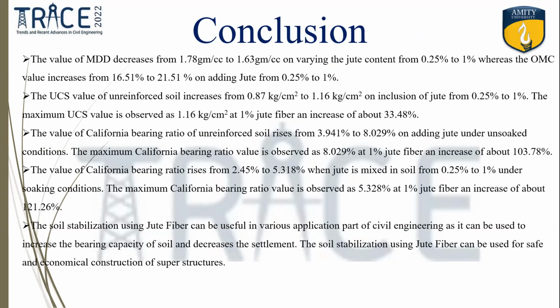The conclusion consists of mainly three things: the MDD decreases and OMC increases, which is quite obvious. And then the UCS value of the unreinforced soil is 0.87 kg per centimeter square, and it increases up to 1.16 kg per centimeter square when the jute is added from 0.5 to 1%. And the CBR value rises from 3.9 to 8.02% when jute fiber is added to the soil. And under soaked condition, the CBR value rises from 2.45% to 5.31% when the jute is added from 0.25% to 1%.